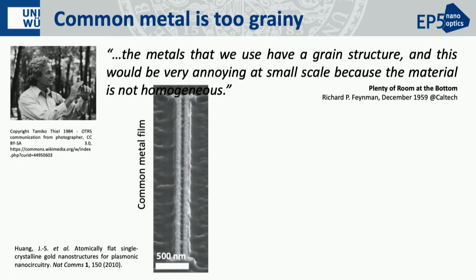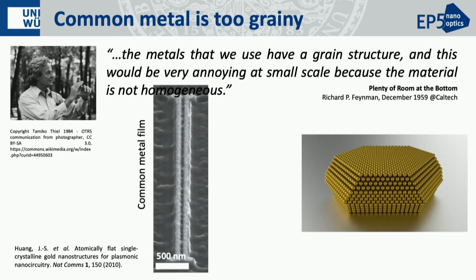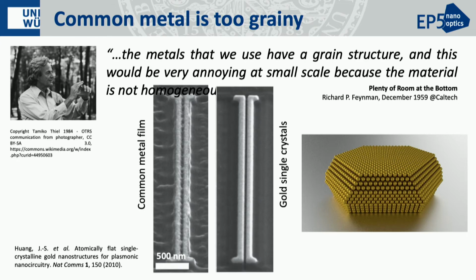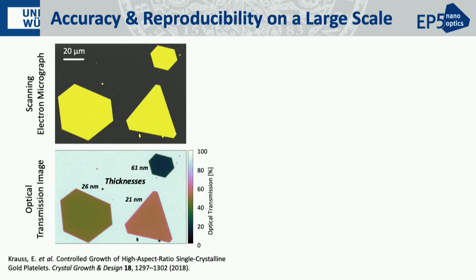The solution lies in using atomically well-defined starting materials, so single crystals, metallic single crystals. And if I use the same structuring for such a single crystal, I can see that the structure is way more accurate and way more homogeneous. So to build such extended optical networks out of it, so really bigger structures, we need that these crystals are at the same time extremely flat, so only a few hundred atoms, on the other hand, laterally really extended over as much as possible, hundreds of microns.